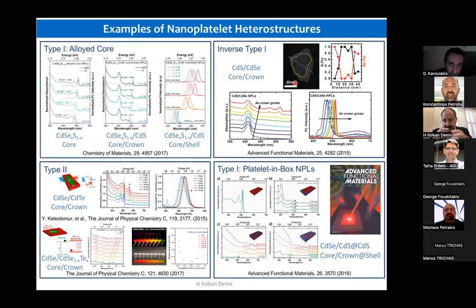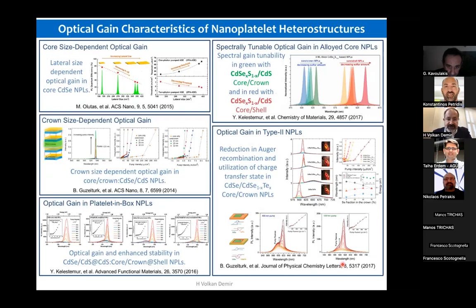These days, we can make it very well defined, quite regular structure. It looks like a quantum ring. So we can confine in a donut type volume both the electron and hole wave functions at the periphery of the particle. Type 2 alignment is again possible. And what I'll show you is this particular platelet in a box architecture, where we combine the two strategies to create core crown shell architecture.